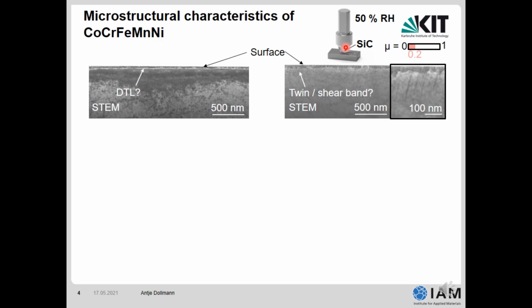You can also see here 2 STEM images, and the TEM foils were again cut parallel to the sliding direction in the middle of the wear track. Here in the first grain, we see again a horizontal line, and this could be a dislocation trace line. Here in the second one, we can see this band-like characteristic. I think it's easier to see here within the higher magnification. So I'm talking about these features. And these could be either twins or shear bands.